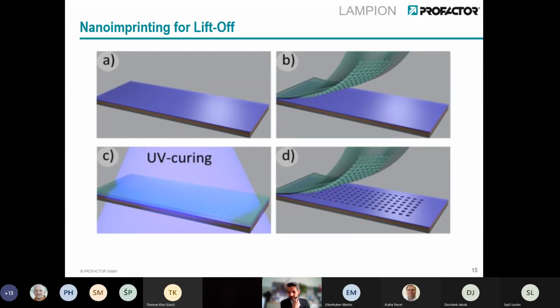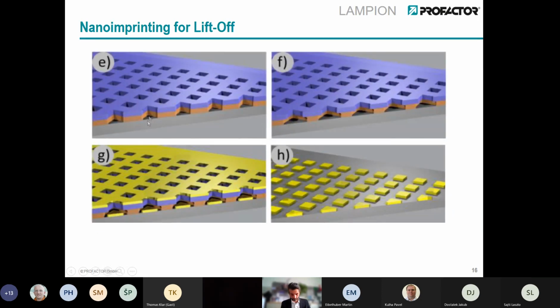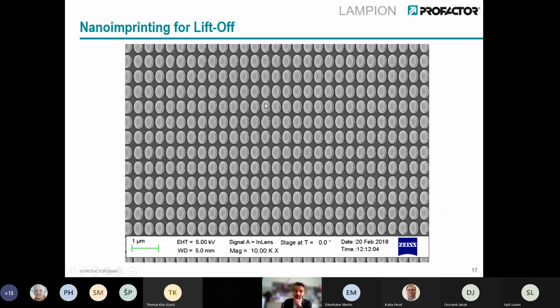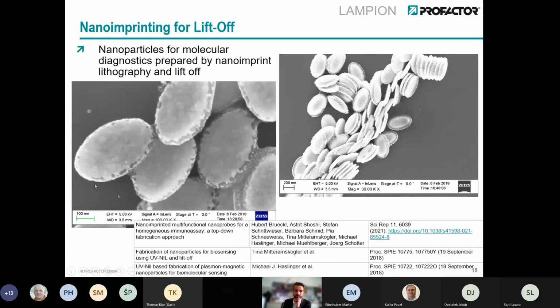And the process was basically very, very similar. So you have a double layer which is coated on the substrate, you do the nanoimprinting, you open up the resist up to the bottom, to the substrate, you create an undercut, again you deposit your material, which again was a multi-layer stack in this case, and you end up with the particles on your substrate. This then looks like this. So in this case, these elliptical particles can then be removed from the substrates and put into solution. Here you see the individual nanoparticles, which were prepared by nanoimprinting and liftoff and then removed from the substrate.